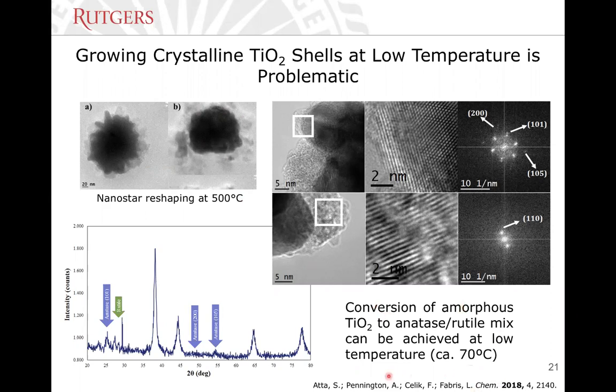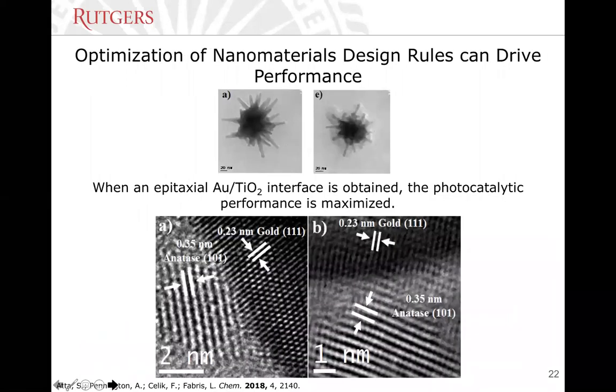In this work, you can see all the details of the synthetic protocols, but basically my student was able to develop a protocol that runs at 70 degrees C and is able to create a TiO2 shell that is a rutile-anatase mix, as you can see in this XRD, and is actually very thin. And as you can see here, you can say almost epitaxially growing. We're not entirely sure, but we can see that the growth of TiO2 on gold resembles epitaxial growth. And you see this very smooth transition from the gold crystal to the TiO2 crystal at this interface. So these are, in my opinion, very beautiful images because it's very complicated to grow these nanoparticles.